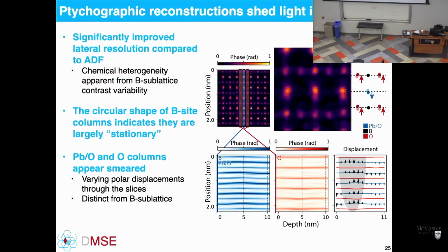So now looking at a small section of a data set from experiment, this is just one region. This is a sum of all the slices that we get out of the sample. So this is a 3-dimensional object that's been squished down to just 2 dimensions. And what you'll notice here is that some of the lead columns look a little bit more smeared out than others. This one seems really sharp versus these down here that look really smeared out. What's going on? Well, we can uncover what's going on by taking line profiles along this direction here, mapping out the intensity as a function of depth.